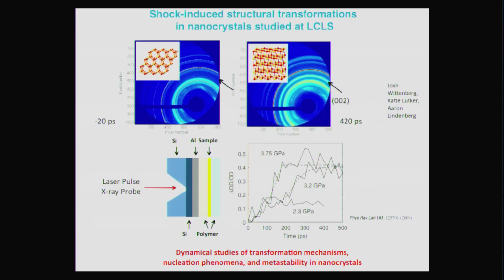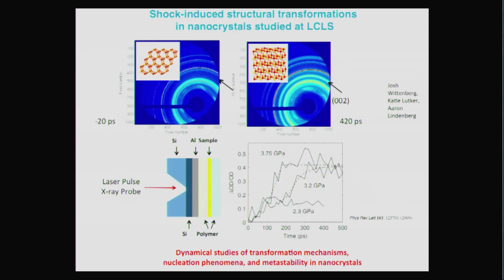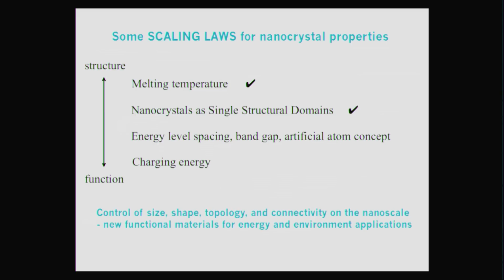And so recently we were able to get a little bit of beam time. It was, I think, 6 hours at the LCLS. And after getting our proposal rejected 5 times, but only because there's so much excitement about using that thing. But in the first experiment already, we could observe the structural transformation, and we're able to induce it with a shock wave. And I'm just very excited because I think we're going to learn about how transformations occur in nanoscale materials in new ways using the new machine. So those are 2 quick examples of scaling laws showing up in energy.